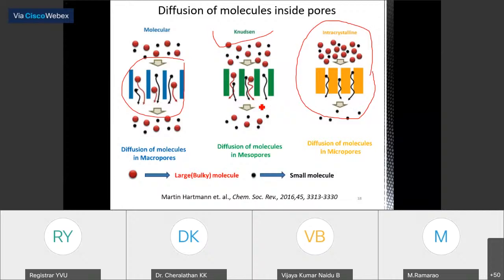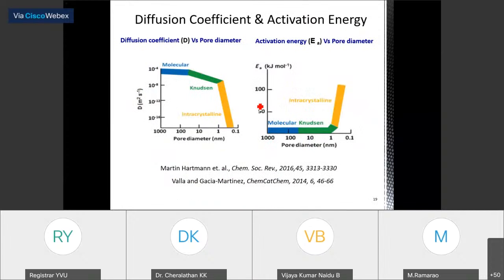And graphically, if you want to understand or explain this, you can have a graph like this. What I have in this graph is pore diameter and the diffusion coefficient on the y-axis. So when you decrease the pore diameter, what happens? The diffusion coefficient is decreasing. In the case of macropores and mesopores, the diffusion coefficient is a little larger compared to micropores because intracrystalline diffusion is difficult in the case of microporous materials like zeolites. So because of this limitation, the activation energy for diffusion increases as shown in this graph. When you decrease the pore diameter, the activation energy is increasing.